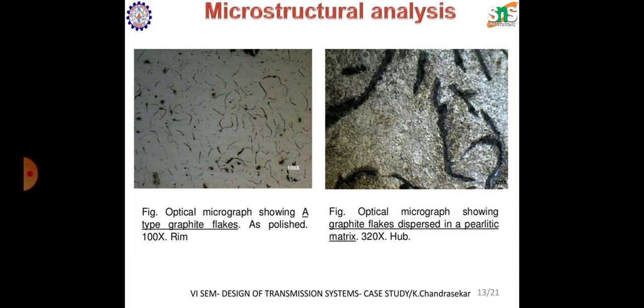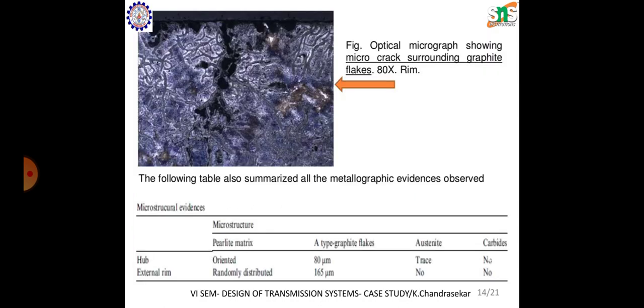Then microstructural analysis was done at the crack surface. In the figure, the first image shows an optical micrograph showing A-type graphite flakes, as polished at 100 times, in the rim area. In the hub area, the optical micrograph shows graphite flakes dispersed in a pearlitic matrix. Then in the rim, the optical micrograph shows micro cracks surrounding graphite flakes. So cracks are found in the rim region surrounding the graphite flakes. The metallographic evidence observed is shown in the table here.